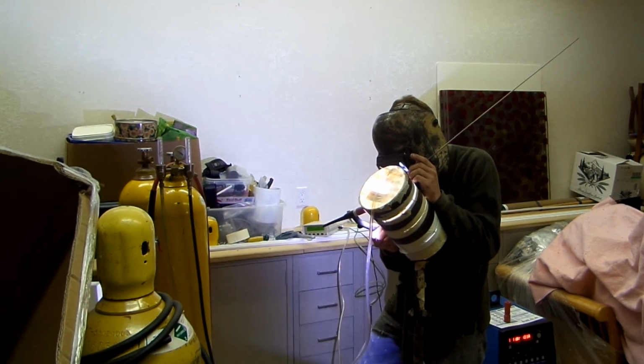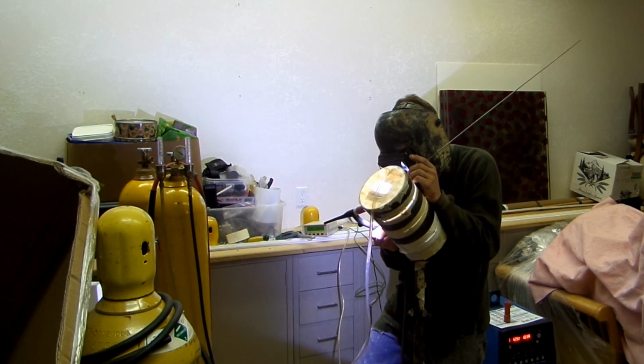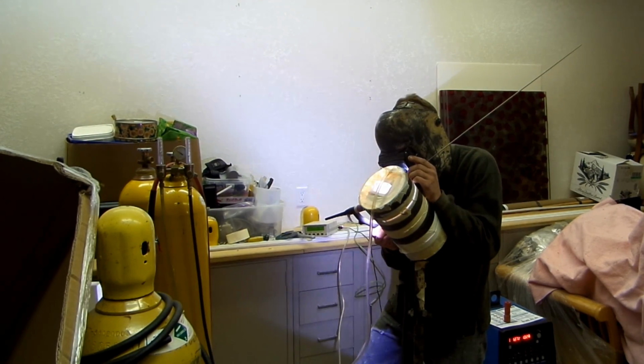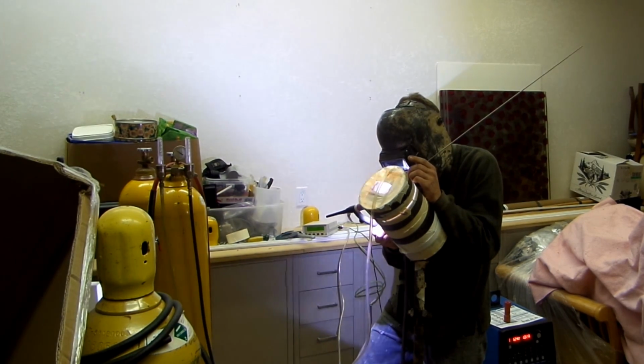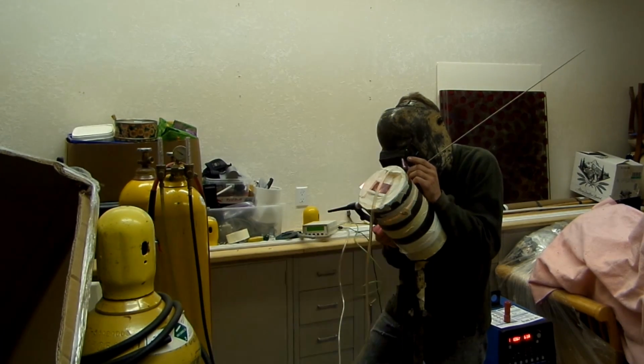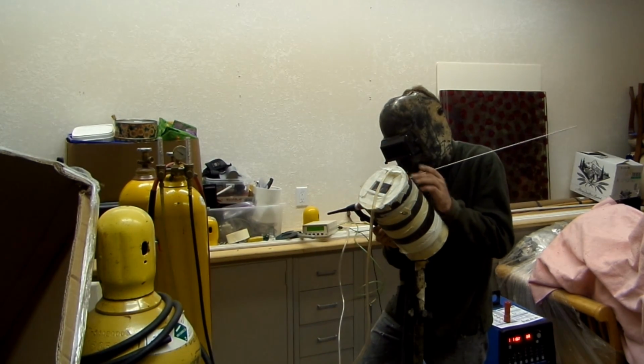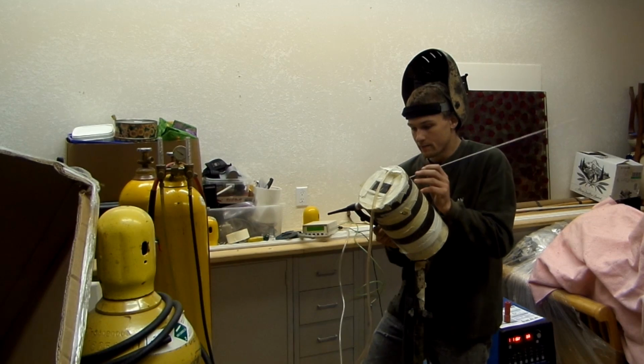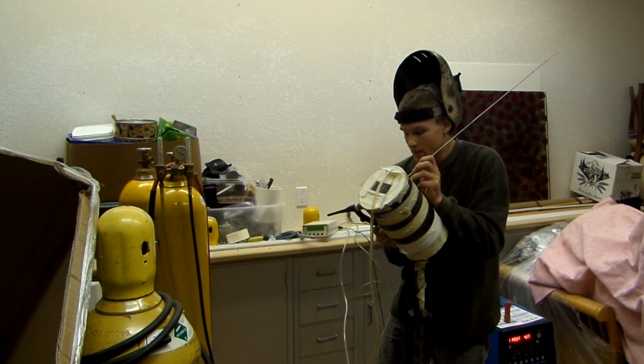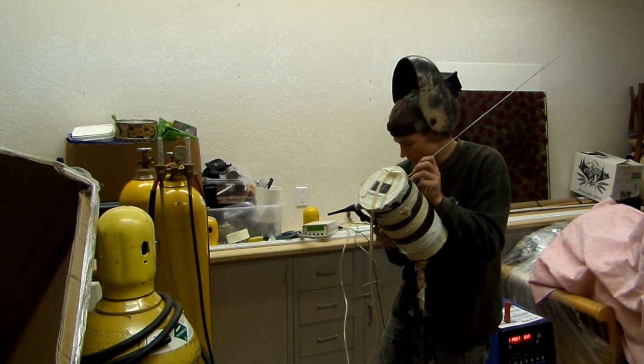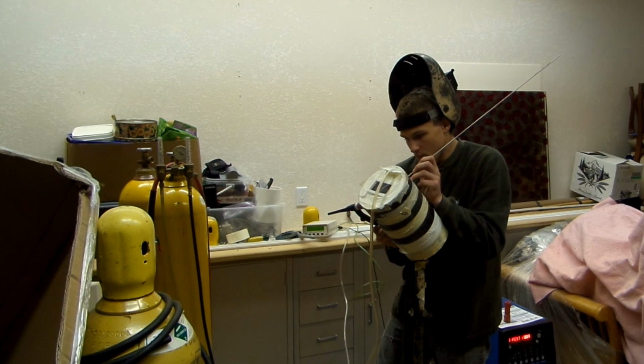base of the puddle. There's a tug of war between the tip of the filler metal, the base of the middle of the puddle, and the big torch from the holding side. I can either hold the big torch in the middle and just wait till the surface tension breaks between the puddle and the filler metal, or else I can move up 1/16 of an inch. My surface tension breaks automatically in between the puddle and the tip electrode. Basically, it just washes out.